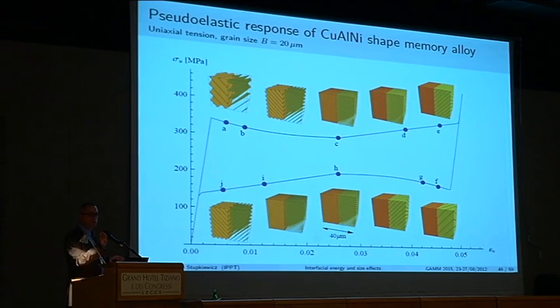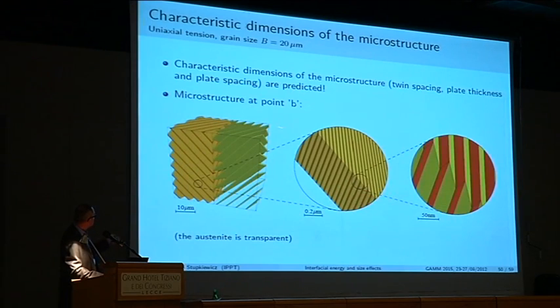By the microstructure, I mean not only the volume fractions of the phases, but the actual thicknesses of the individual elements of the microstructure. So here is the close-up. The austenite here is transparent, and you see the thickness of the plate, and this is the scale, 10 microns, so the thickness is probably below 1 micron. Here you see again the plate and the scale for the twins.